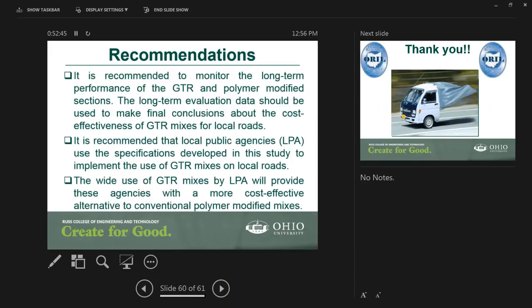Our first recommendation is that we have done a performance evaluation for, I would say, a year and a half of service. These are basically preliminary findings, and do not cover the long-term performance of those mixtures and sections. Therefore, we're recommending that those sections should be evaluated. We provided in our report a plan to do the long-term evaluation of those test sections. Based on that evaluation and the cost analysis, we can determine whether the GTR asphalt mixtures are cost effective or not. But again, based on the preliminary findings, we can see that there are no issues, and we think that they can be used.